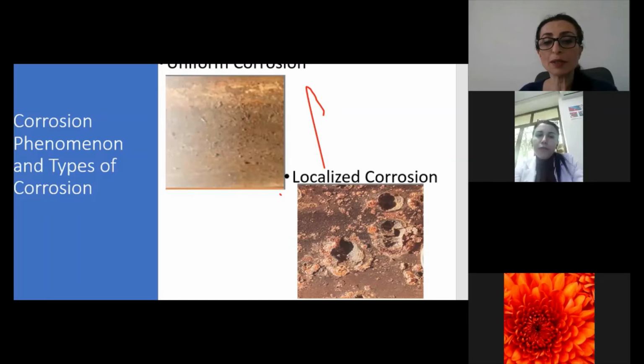Localized corrosion is identified by small discrete sites of metal loss at fixed anodes. You see in the right bottom of the slide an example of localized corrosion, and you see pits, small holes. This is mainly the anode area of corrosion. We'll talk about localized corrosion mechanism later. Metal surfaces surrounding areas of localized corrosion show minor or no apparent attack. Also, pitting can occur within areas of general corrosion as well. So it's like carbon dioxide, oxygen, microorganisms, chlorides attack. With all of these mediums, we are experiencing pitting corrosion.